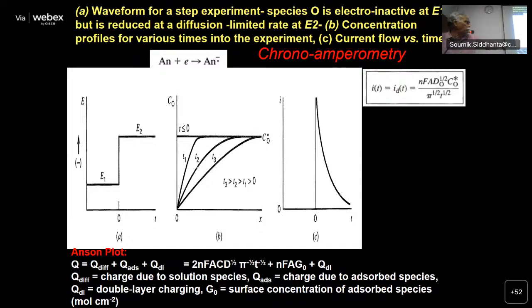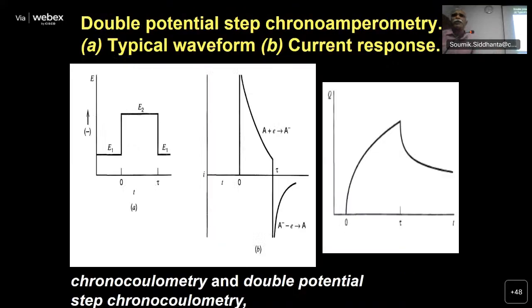You can see below the expression. The images are more or less similar. The only difference is that instead of current, I am plotting charge. What is interesting is from total Q, I can get Q diffusion. Only the diffusion part I can separate. Q adsorption part I can separate, and Q double layer. So all these three can be quantitatively separated if I plot charge versus time. Again, I'm only showing a snippet of this. I will not go into the details.